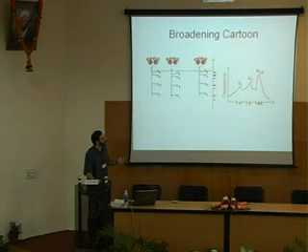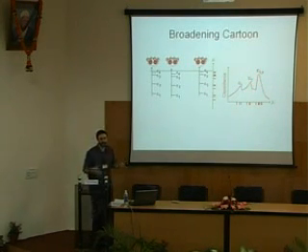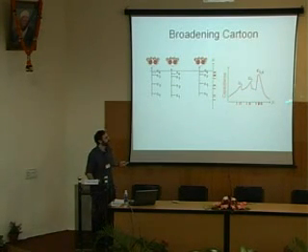If on average the first electron energy is clustered together, I'll still see something in my measurement. If on average the second electron addition energies are clustered together, I'll still see something. In the schematic, epsilon 3 and epsilon 4 are so close together that they're not well resolved. And of course, I copied the real-life situation. Epsilon 3, epsilon 4 are fairly close together. They're both very weakly bound electrons, and so our measurement doesn't resolve them. This is my conjecture for peaks A, B, and C.